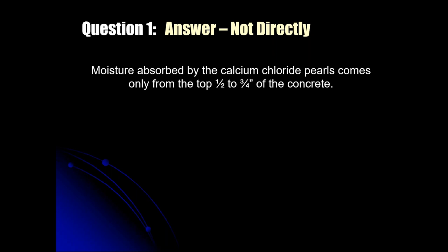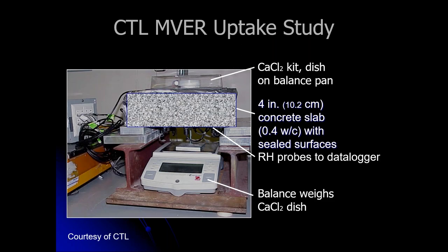And what we've learned is that this test is only affected by moisture in the top one half to maybe up to 3/4 of an inch in the concrete. And that research was conducted by Howard Kinnear and Scott Tarr, good friends of mine, who are no longer at Construction Technologies Laboratory, now called the CTL Group.